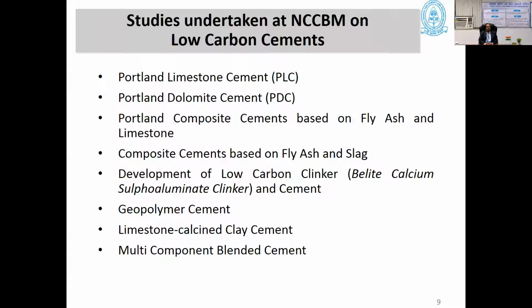So we think that by utilizing this fly ash and limestone, there is a potential for the reduction of carbon dioxide emission. Then develop low carbon clinker, belite calcium sulfoaluminate clinker and cement. This is a new type of clinker NCCBM developed, because for the last 50 years we have been producing high alite clinker, as a result of which we are utilizing high grade limestones, and our thermal energy is also high, like 1450 degrees centigrade, and carbon dioxide emission is high. So now by developing this low carbon clinker, there is a potential to reduce carbon dioxide emission by 30%, and also thermal energy can be reduced by 200 degrees centigrade.